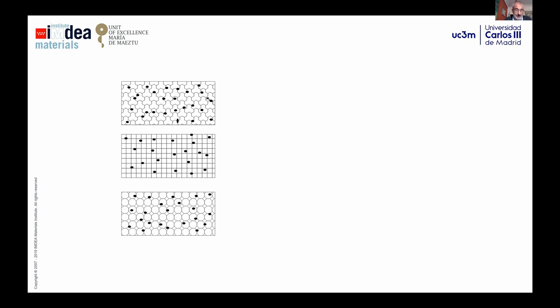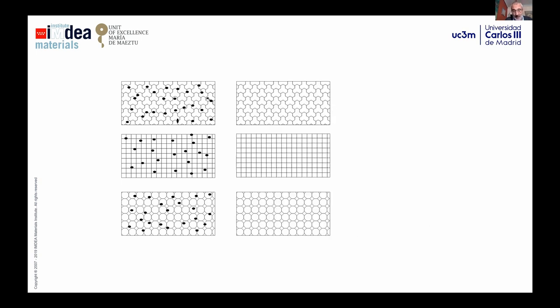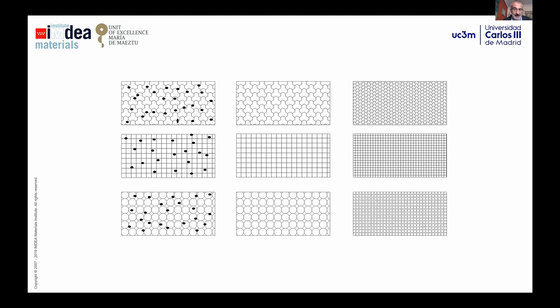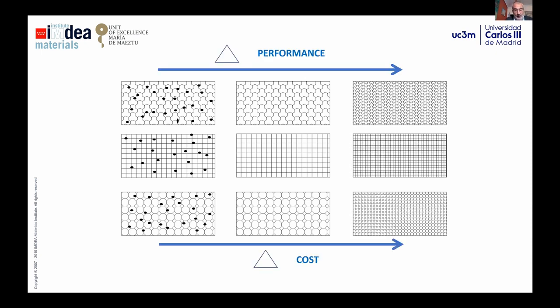But of course, during this lecture, I will try to show you some methods in which we can get a lower level of porosity using powder metallurgy. We can go from this situation to that one in which we have a non-textured microstructure, but without porosity. Or we can even get microstructures with a grain size much more reduced than in conventional forged material or conventional powder metallurgy materials. So on the right, we will have the best material that can be obtained, because we have a non-textured material with no defects and no porosity. Of course, we can increase the performance in that way, but we will also increase the cost.